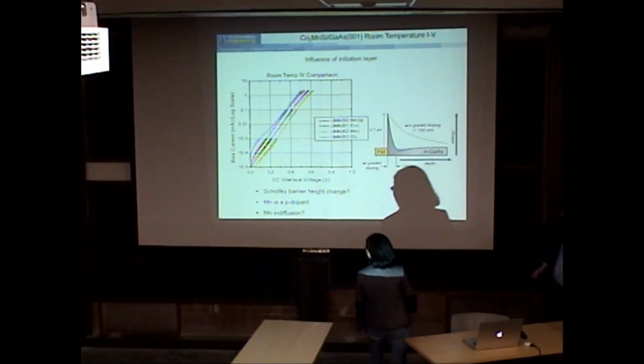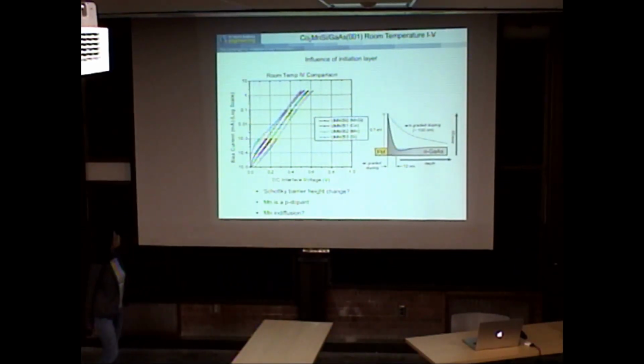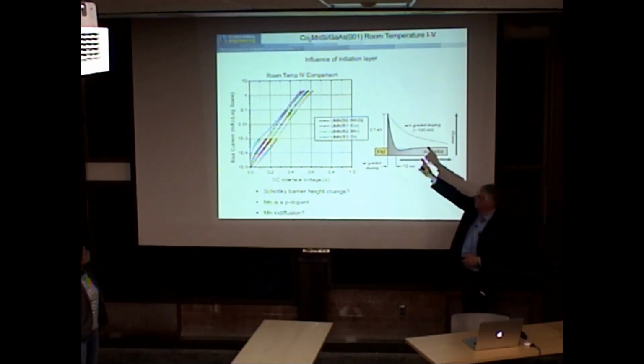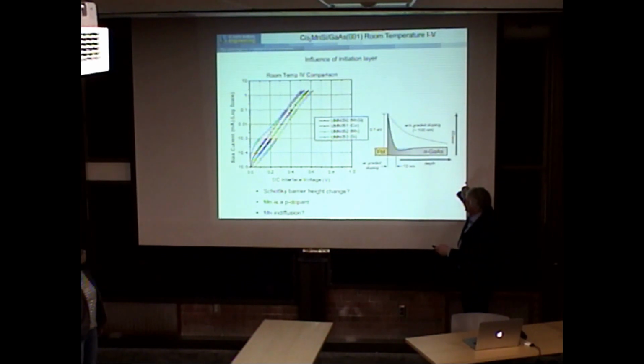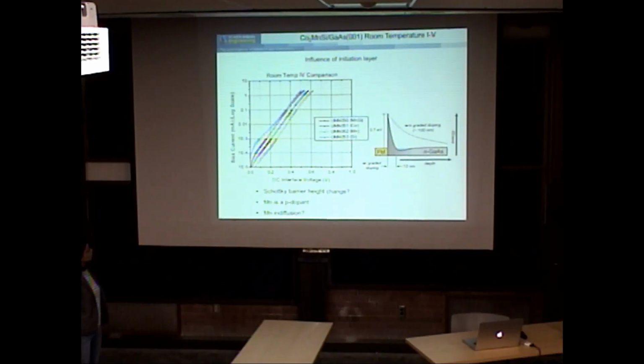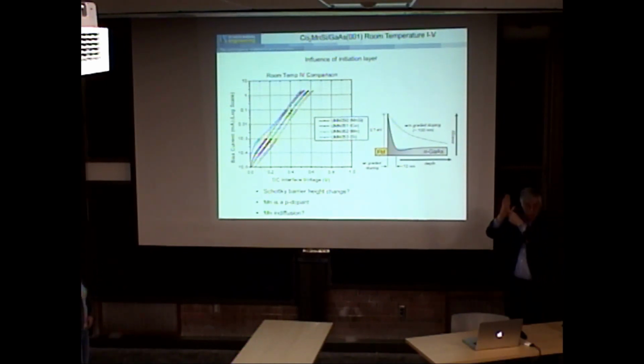So here, you'd extrapolate back from doing the IV measurements. We were trying to look at the effect of manganese first, silicon first, etc. The barrier height here would probably come out more like an effective barrier height because of the high doping, probably more like 0.3 eV. 0.3 eV is my guess. Where the peak is, 0.7, because we're tunneling through the Schottky barrier. We made it thin enough that most of the carriers are tunneling through the barrier, not at the Fermi level, but some distance up. So they're semi-Schottky like.